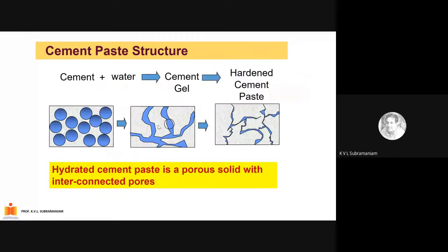And then if you look at the microstructure of cement, if I put cement in water, this is a representation of that hydration process. Initially, I have cement grains sitting in water, which I've idealized as these circles or spheres. With time, the cement is consumed, and what I end up with is a porous network, which is basically a network of water-filled tubes. These water-filled tubes are on the size of microns and even smaller. In fact, they go down in size to a few nanometers and fractions of nanometers. So you get these small water-filled capillaries which go from nanometers up to micrometers. And with time, as more and more cement reacts, water is consumed, and the capillary pore space starts decreasing.